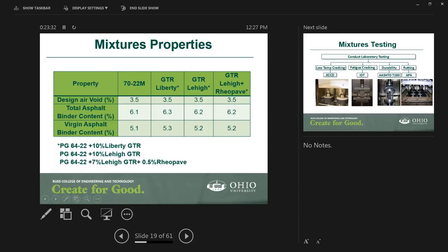This is the design for the different asphalt mixtures. So we had a control mixture with a polymer modified 70-22M. The 70-22M binder was obtained from a contractor that has used it on a project on local roadways, and then those are the different mixtures. We used the GTR Liberty, Lehigh, and Lehigh Rheopave, with the percentages that are shown here, and they were tested with a binder. Marshall mix design was used for designing those asphalt mixes. And this is the virgin asphalt binder that you can see. We have differences of about 0.1 to 0.2 in the optimum asphalt content between a GTR modified asphalt mixture and a polymer modified one.